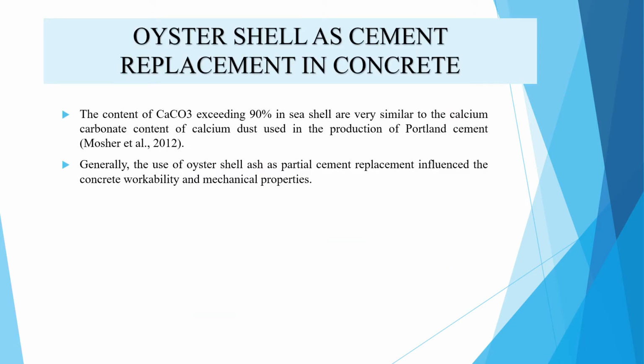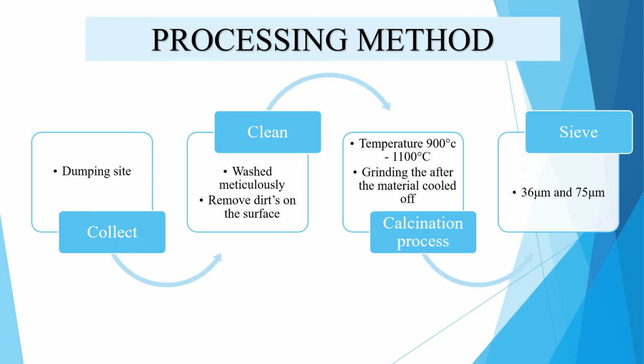These are the properties of oyster shell based on past research. Oyster shell as cement replacement in concrete. Based on Mosher et al., 2012, the calcium carbonate content exceeding 90% in oyster shell is very similar to the calcium carbonate content of calcium dust used in the production of Portland cement. Generally, the use of oyster shell ash as partial cement replacement influences the concrete workability and mechanical properties. This is the processing method to produce oyster shell ash as cement based on past research.